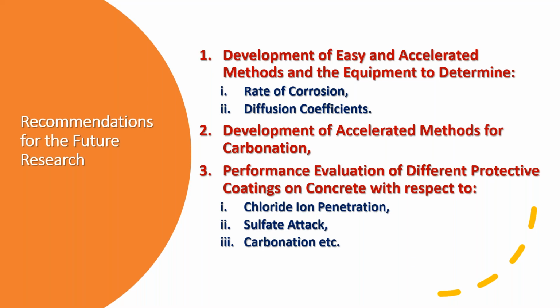Development of easy and accelerated methods and equipment to determine the rate of corrosion and diffusion coefficients. Right now, an easy method is not available, and also an accelerated method. The rate of corrosion you can only measure in a sophisticated laboratory, and in an ordinary laboratory it is very difficult to measure. And also for diffusion, we have to develop easy methods to calculate the diffusion coefficient. And development of accelerated methods for carbonation, easy methods, and also performance evaluation of different protective coatings on concrete with respect to chloride penetration, sulfate attack, carbonation.